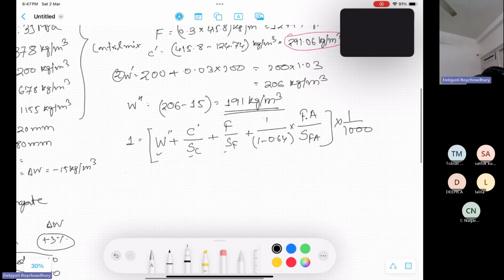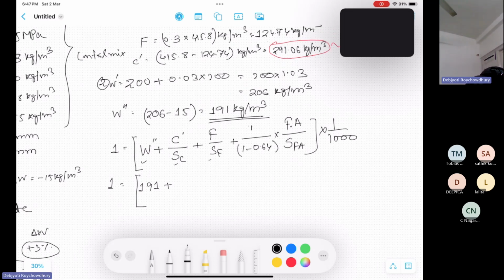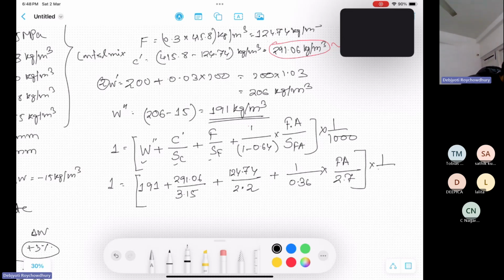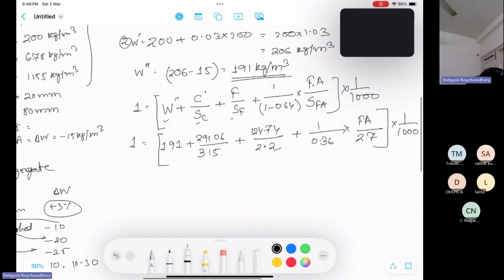So for fine aggregate content, I am writing this. W was 191. And what is the new cement content? The new cement content is 291.06, and specific gravity of cement is 3.15, plus fly ash content is 124.74 kg per meter cube, and specific gravity of fly ash is 2.2, plus 1 by 0.36 is fine aggregate. We have to find out the fine aggregate content, and specific gravity of fine aggregate is 2.7, right? So 2.7 is this. If you calculate, it will come like this.